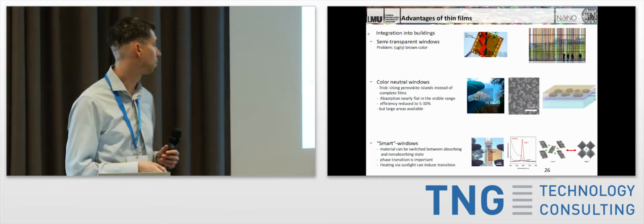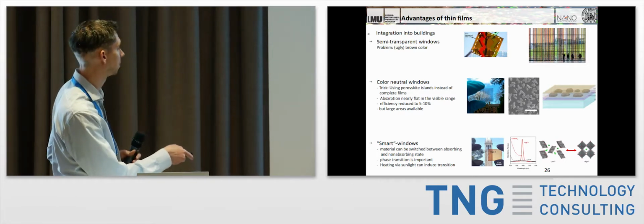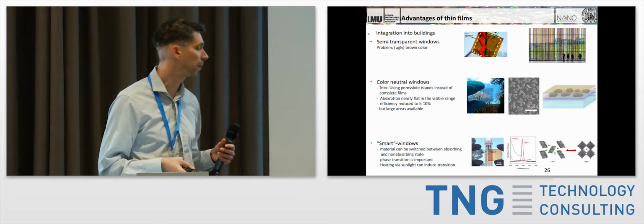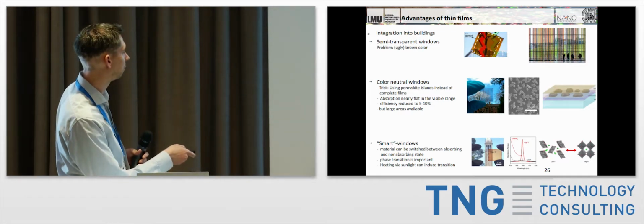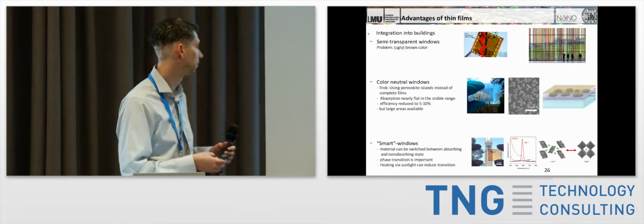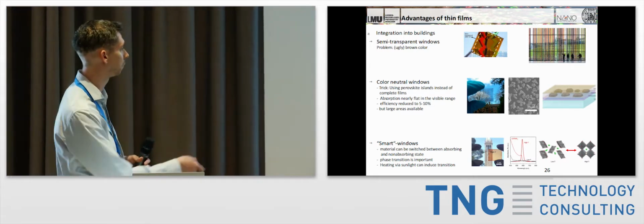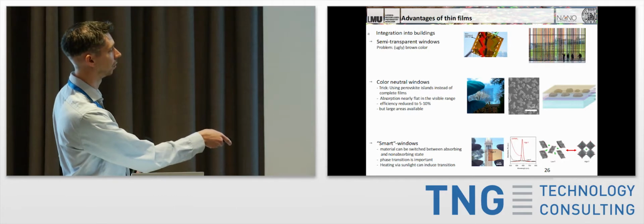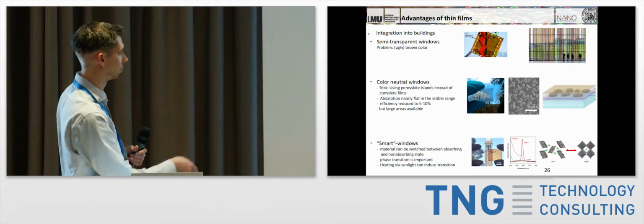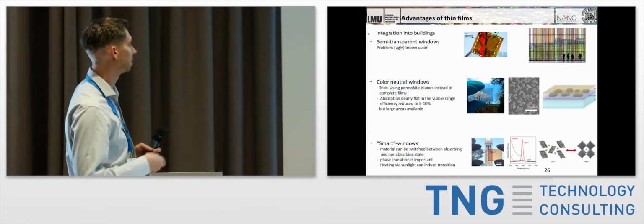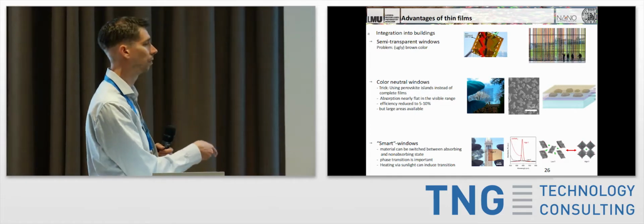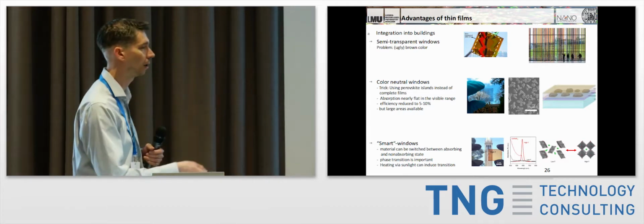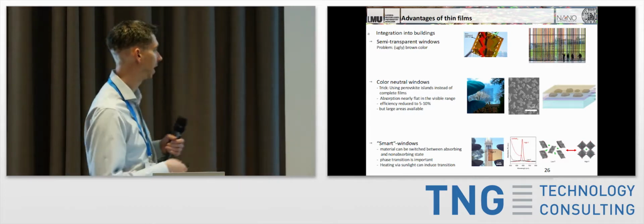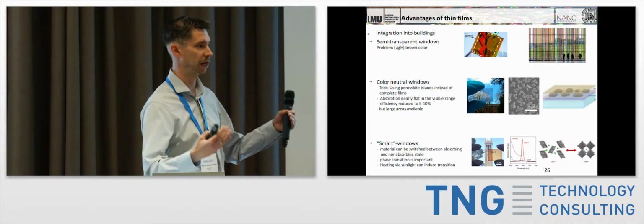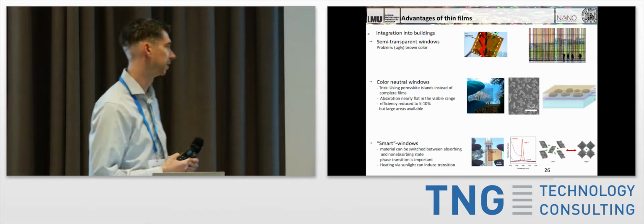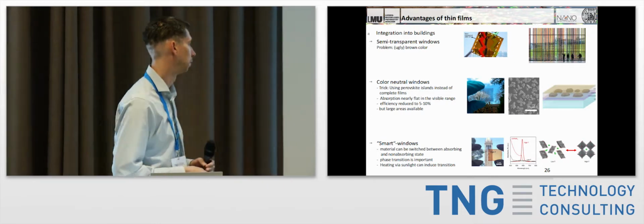Another idea is to use so-called smart windows. There's a material, also a perovskite, that can be switched between an absorbing and a non-absorbing state. The important thing here was that this was essentially done by a phase transition, the transition between two different configurations of this crystal. So this is the normal perovskite form that you can see, and this is a so-called 0D state. And this is actually achievable only through heating from sunlight. So this perovskite itself can absorb light. It goes into an absorptive state, and then can be used as a smart window, for example, during the day. If it's too bright, then it can dim the light that's coming from the inside, sort of like a pair of photochromic sunglasses.